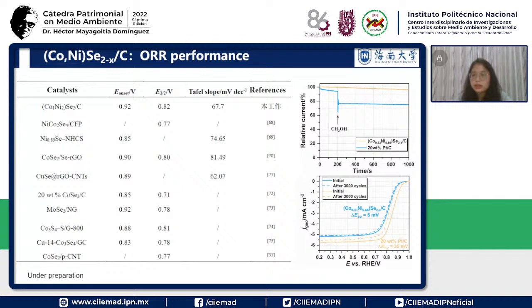So we did the work. We can see after the addition of the methanol, this material shows a negligible change, almost a straight line. But for the platinum, we know the platinum is not stable in methanol or ethanol, the alcohol solution. And for the stability, we tested after 3,000 cycles. This material has not changed too much. The half-wave potential only changed 5 millivolts, but for the platinum it is 35. So we can see our material is good. It also shows good methanol tolerance and stability compared to the platinum.